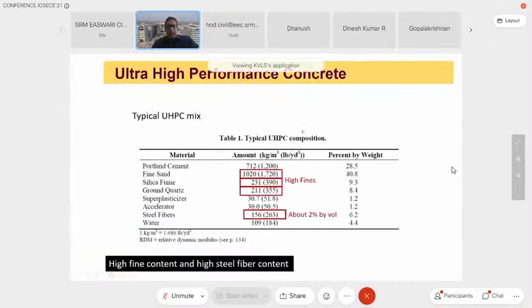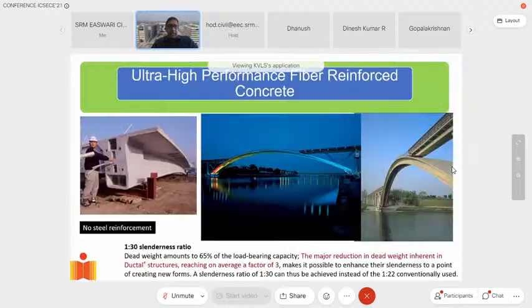Just to show you a typical ultra high performance concrete mix where, of course, now we are engineering the material. So in this ultra high performance concrete, we don't use coarse aggregate, we use a lot of fine aggregate. One needs to use a lot of fine materials like ground quartz and silica fume. And of course, there's a very heavy requirement of processing. Processing is very different, or the way it's mixed and placed is very different compared to conventional concrete.